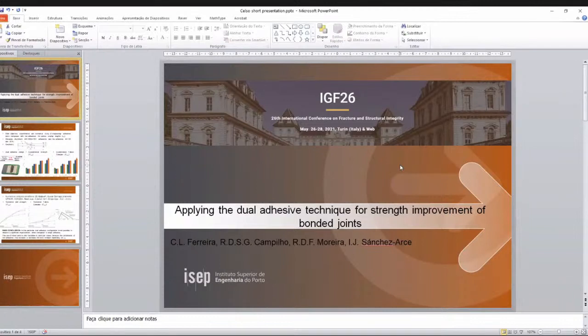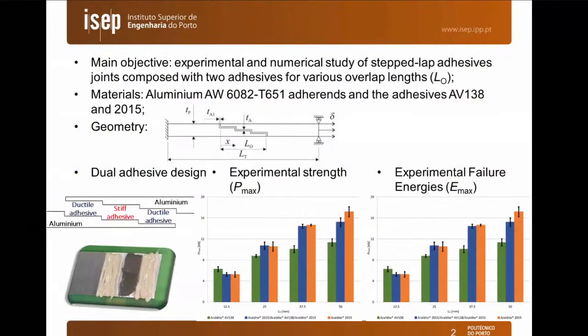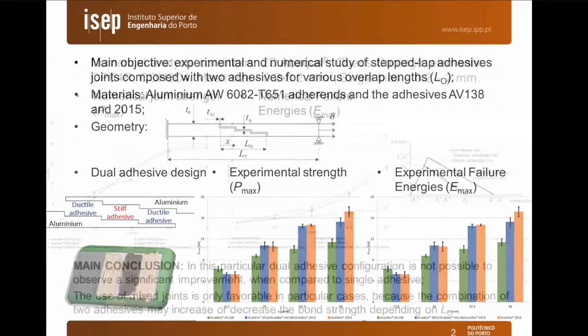I'm doing the presentation Applying the Dual Adhesive Technique for Strength Improvement of Bonded Joints. The main objective of this work is to determine experimentally and numerically the step adhesive joints composed of two adhesives for various overlap lengths. We studied 4 different overlap lengths: 12.5, 25, 37.5, and 50 millimeters. The material used for the adherends was aluminum alloy, and the adhesives are the AV138 and 2015. The main advantages of the step lap joint are the decrease in peel forces and also the decrease of the stress gradients. The main disadvantages are the difficulty in machining, bigger manufacturing time, and a more expensive manufacturing process.